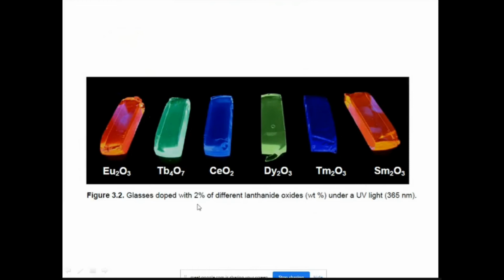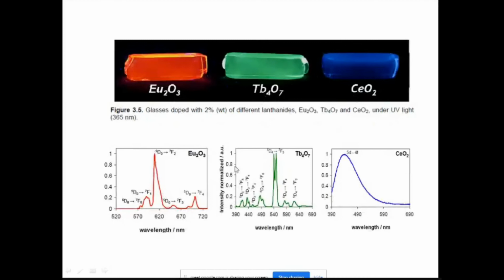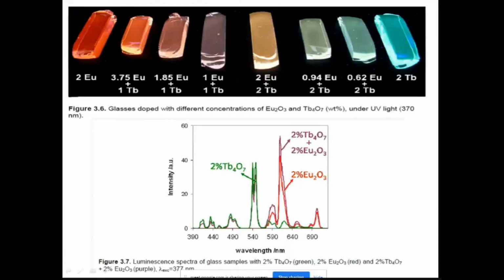And now, if you go to the next one, europium, terbium, and cerium, this is the absorption or emission spectra. You can see not only does europium give red color, it also gives other colors. Out of the other colors, red is dominating. Similarly, in terbium, green is dominating. In cerium, blue is dominating. And now, europium gives red color, terbium gives green color. If I add them together and change the composition of europium and terbium, I can tune from red to green or green to red. This is the way research is going on. And depending upon the environment also, the colors are changing.